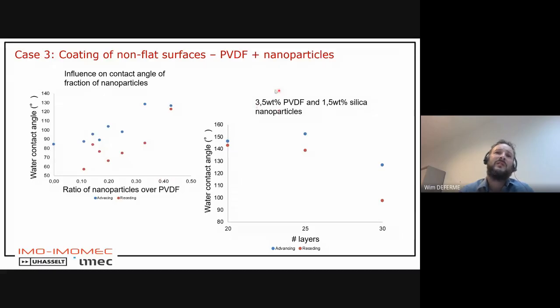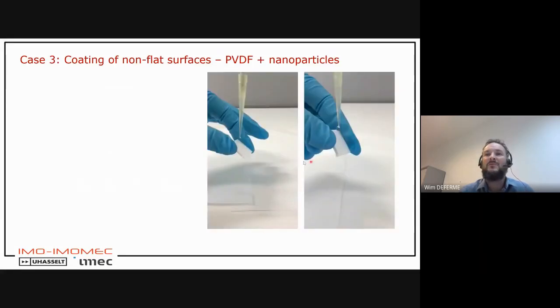And then, of course, if we take 3.5 weight percent of PVDF and 1.5 weight percent of silica nanoparticles, we achieved 140, 150 in advancing and receding contact angle. And even with 20 to 25 layers, we have super hydrophobic behavior. And that's what you see here.